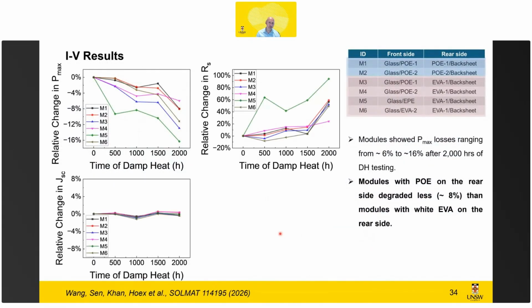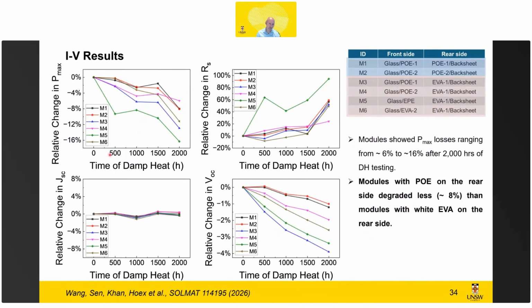The interesting part was that we saw degradation. So it's 2,000 hours. So the worst BOM was 16%. Of course, these are mini modules. So typically the losses at the mini module level are higher than the large module level. But the main thing we have to look at is that there's quite a big spread, and some BOMs are doing a lot worse. But then the most interesting thing we saw was that there was also significant loss in VOC, so up to 4%.